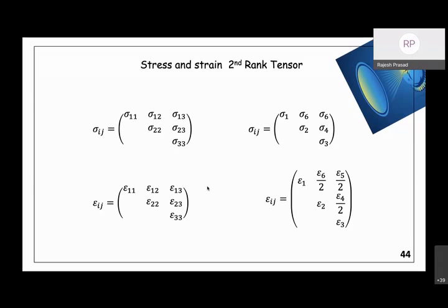So there is also another question in the chat from Professor Nayak. He's saying that these are single crystal considerations, so how do they relate to polycrystalline solids? Yeah, that's another ball game, Professor Nayak. We have also attempted that in our other paper, which means one can think of averages or some sort of average moduli. So averaging again is not easy. So one thinks of averages under special conditions. That gives the Voigt average and the Reuss average and things like that.